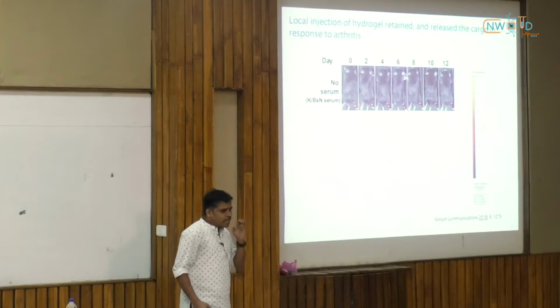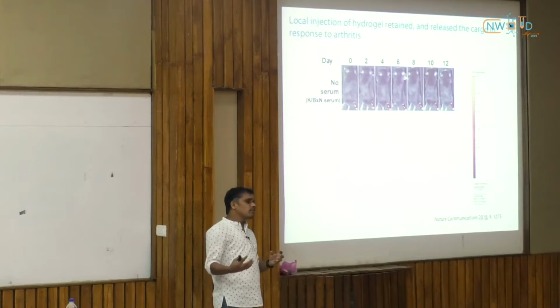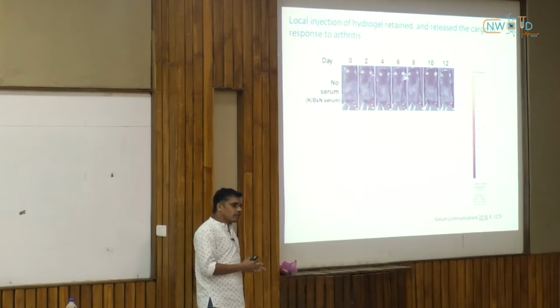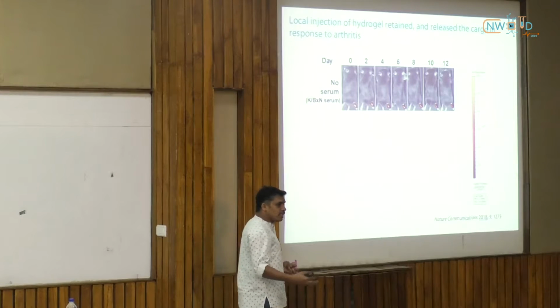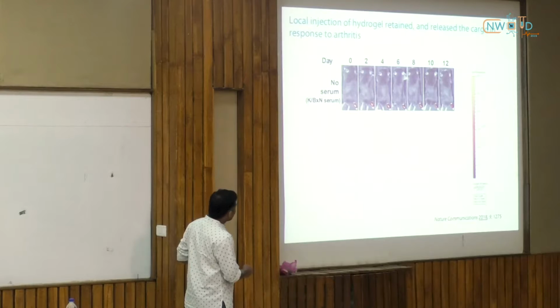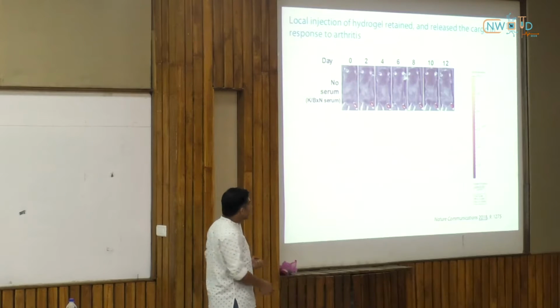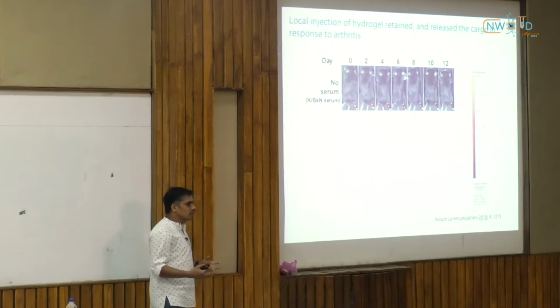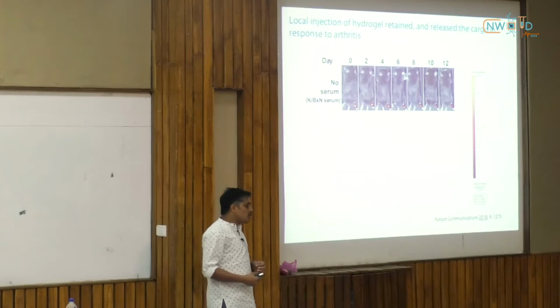Another critical parameter to evaluate is whether, if there is no inflammation, the gels stay there and localize your entire drug, and don't disintegrate to release it in a non-specific manner. To test that, you take animals and dye-encapsulated gels. You give intra-articular injections, and even after 2 weeks you don't see dispersion of the drug or the dye, and it remains localized in the joints.